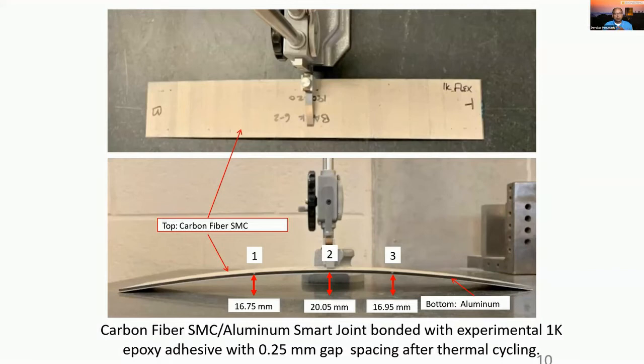The same way for composites, whether it's carbon to carbon or carbon to glass or carbon to metal, because of the differences in coefficient of thermal expansion and other variables, you have this mismatch of CTE often leads to very, very large residual stresses and strains in the joint. Here I'm showing you an aluminum joint with a carbon fiber sheet molding compound. And because carbon fiber's CTE is much lower than aluminum, if you don't accommodate for that CTE mismatch in the adhesive, then you end up with problems like this.